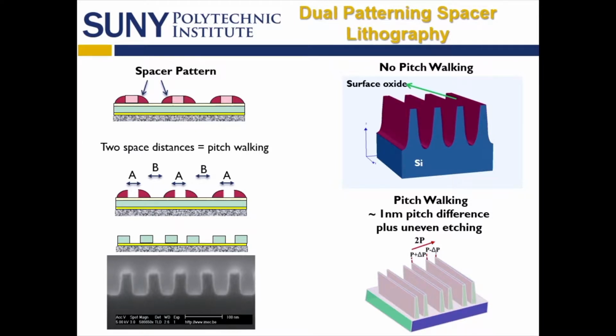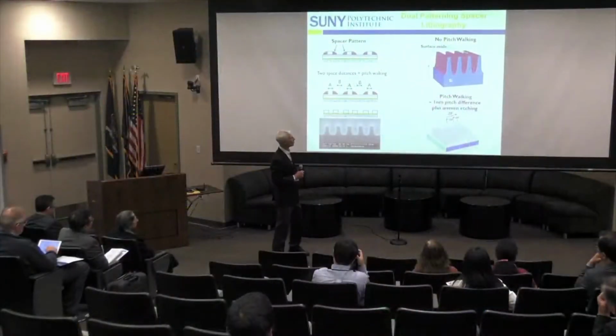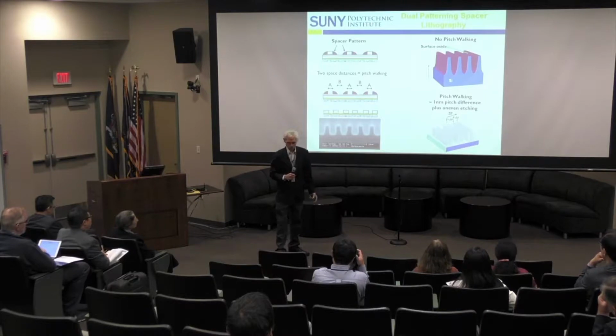And because you can have two different spacings due to the spacer oxide patterning process, you get pitch walking, as you see in the bottom right of the image. If you've ever looked at a TEM image where there's only a nanometer of pitch difference between the normal pitch you'd expect and the pitch-walked fin, it's, at least for me, visually difficult to tell.